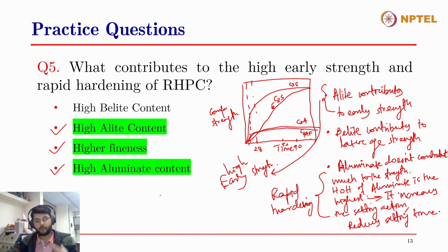But you'd have also seen that when we compare RHPC and OPC, the A-lite and the aluminate contents are almost similar to that of OPC. So what contributes to the higher early strength then, if the A-lite and aluminate contents are still comparable with that of OPC? It is the higher fineness. So the last option is higher fineness.